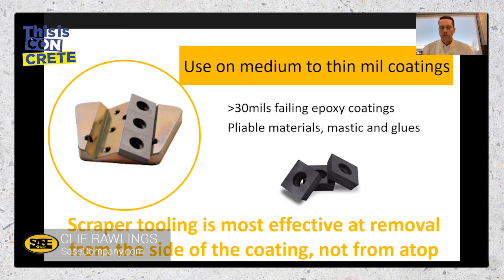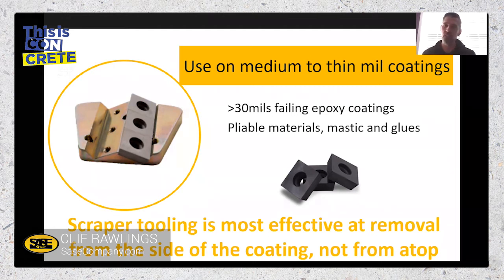Yeah, and you should see some differences when you're doing that. I mean, you'll see that the faster you go, the more coating you're cutting, up to a point. At some point, sometimes you'll see that it stops cutting, and that's because either you're heating it up too fast or you're just sliding across the top and not giving the coating time to tear. Absolutely right. I think one of the best analogies is the boat and water. The faster the boat goes, the more it planes up and the less the boat's in the water. The more you slow down, the more of the hull is in the water, and in this case, same thing with the diamond. So if you go slow enough, you may be cutting deeper and cutting more efficiently. If you spin too fast, you're planing up and you're skating on the top surface and barely scratching it. You're not removing as much. So there is a happy medium between those two points somewhere.